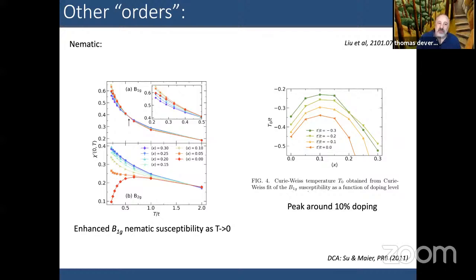Likewise, there's been a lot of effort looking for nematic order, and this is encouraging: there's a very strong increase in the B1G nematic susceptibility. That's chi prime as a function of temperature plotted here for different values of doping. So there is a strong rise as one goes down to lower temperatures. It's not as prevalent as in B2G or a different type of nematic susceptibility. And in fact, it's even non-monotonic, in that there seems to be a peak if you extract a Curie temperature from this, somewhere around 10% doping.